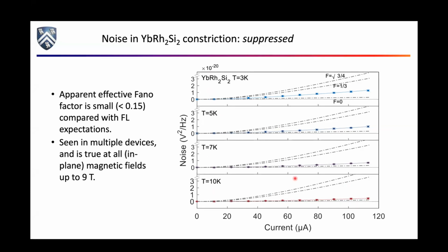If anything, this thing is very, very quiet. What you see is the Fano factor is practically speaking 0, almost 0 by the time you get to 10 Kelvin. And it's still quite suppressed by the time you're down to 3 Kelvin, though it does seem to be coming up a little bit as you cool. Okay. And we've done this in multiple devices made from multiple films. We've swept magnetic field. Magnetic field does change the resistance because there's this magnetoresistance, but once you account for that, it doesn't change the noise at all. That data is all in the SI for the paper.